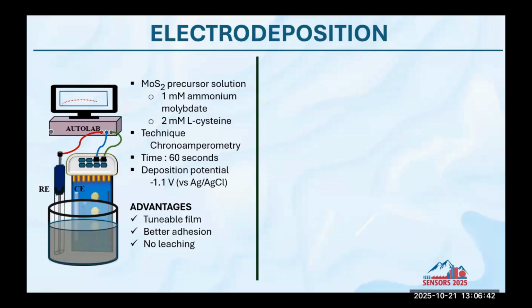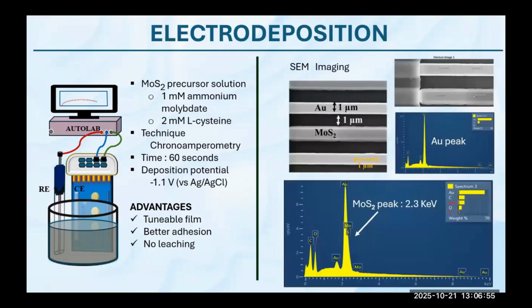We can have a very finely tuned deposition on the electrodes, and we can control what length, what depth, and what type of deposition we want. Now, to confirm the deposition, or the precursor which we used, we did a SEM characterization. And as we can see, we are depositing only on one side of the comb. These are interdigitated electrodes, so we are using just one side of the comb.